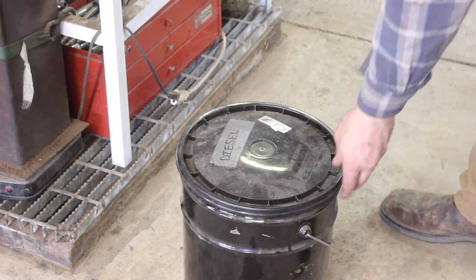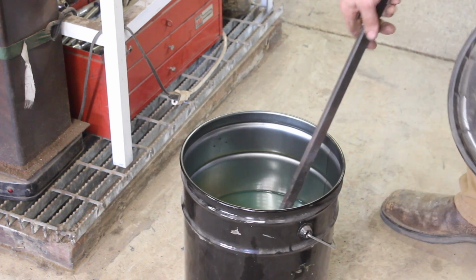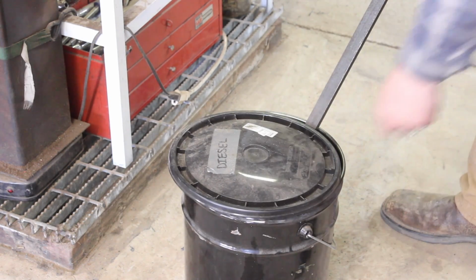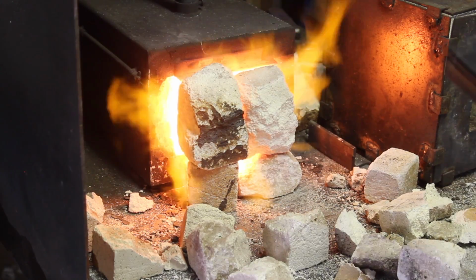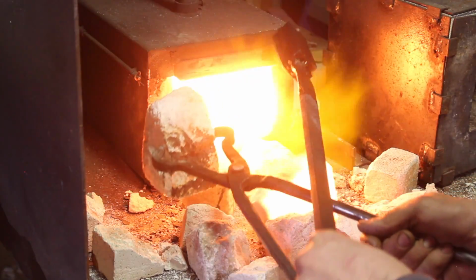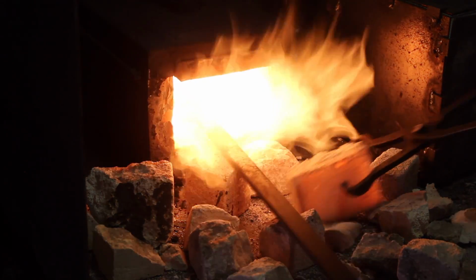In this case, I went ahead and cut the center piece of steel a little bit longer so it could hang off the back of the billet and hopefully keep the arc weld there from interfering with our forge weld on our Sanmai billet.